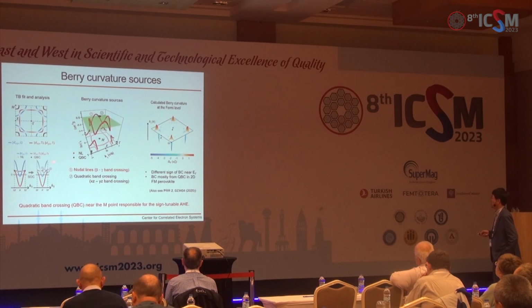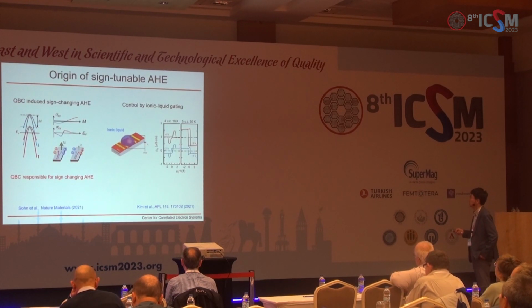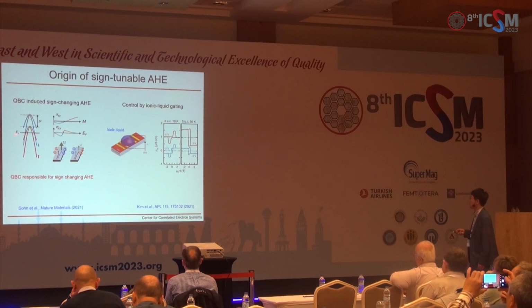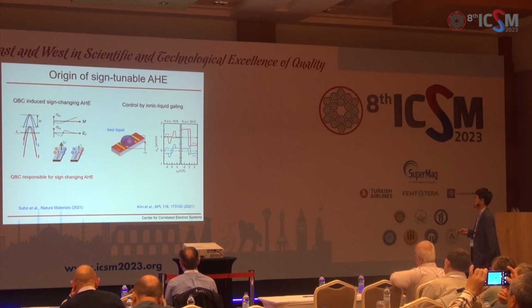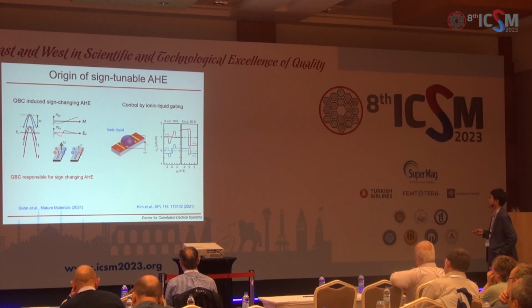So this helps to understand the sign-tunable anomalous Hall effect. Let me show you what happens. Here is this quadratic band crossing, and here's a majority band and a minority band, and they are split by exchange interaction. And there's also a Fermi level, and as you change the splitting or the position of the Fermi level, that affects the anomalous Hall conductivity.